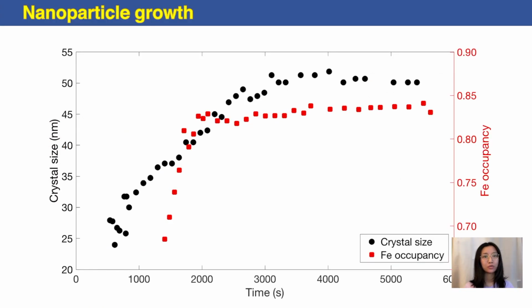One thing that I want to note is the crystal sizes of our synthetic hydrohematite were tens of nanometers. The crystal size plateau has a rough correspondence with the iron occupancy achieving the steady state. Our interpretation is that nanoparticles can retain deficiencies better than mature and well-developed crystals.